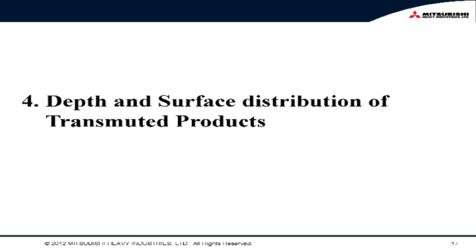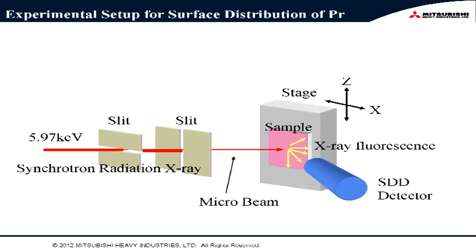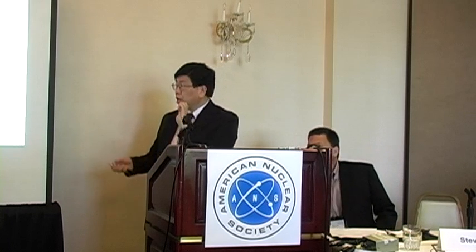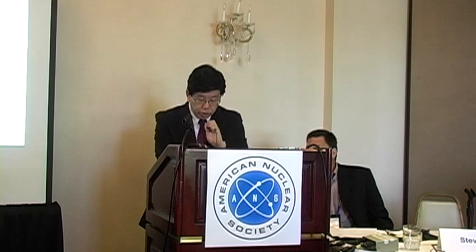Okay, so I will explain the surface distribution and depth distribution of praseodymium. This is the experimental setup for the surface distribution of praseodymium. We use 5.97 keV synchrotron radiation X-ray, and we use a slit to get a microbeam. We put the sample on the XY stage, and if we move this stage, we can measure the surface distribution of praseodymium.